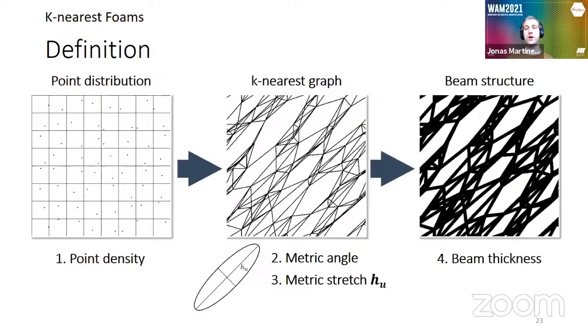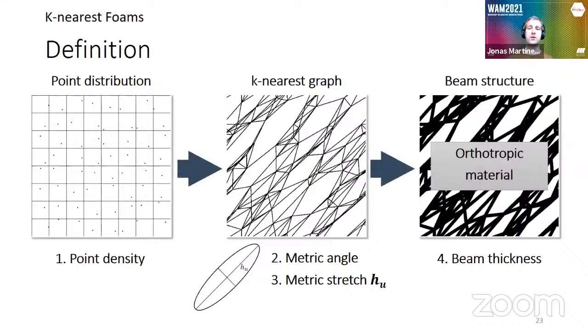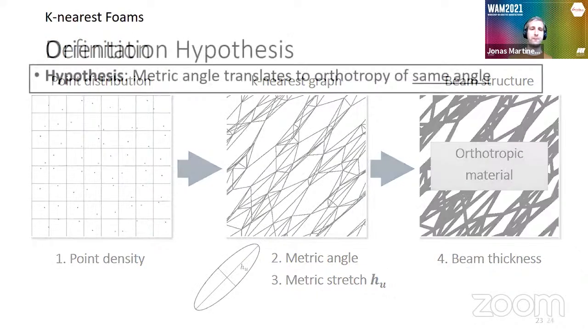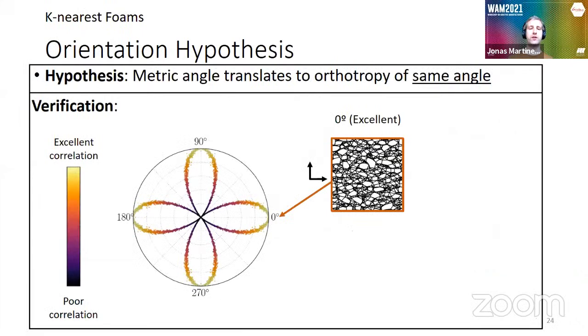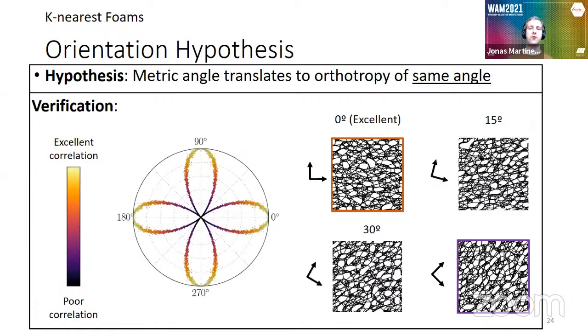And finally, we have another parameter, which is the beam thickness. So this leads us to a structure that has an orthotropic behavior. And more interestingly, the orthotropic axis is aligned with the metric angle. So this is what we verified here. As you can see, we have different angles. And I'm not going to enter into details of this plot, but basically it shows you that the orthotropy is aligned with the direction of the stretch of the metric.